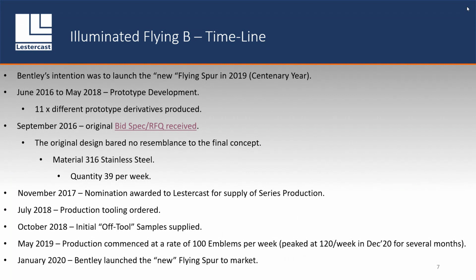October 18 was initial first off samples, and May 19, production commenced at a rate of 100 emblems per week, which, as you can see from those figures, is significantly higher than where the Mulsanne has ever been. We did actually peak at 120 a week in December 20, which was quite a challenge because everybody was coming out of COVID. We've got skeleton crews running, and Bentley were putting pressure on to say we want to build this stock up ready for launch at the end of 19. And we were achieving these sorts of numbers with limited staff, and it was quite a challenge, but we got there.